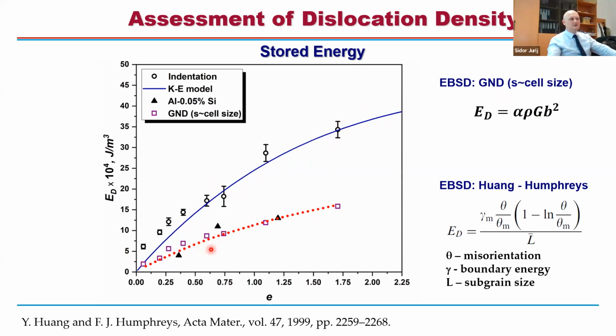And then I looked at the papers which were published almost 2 decades ago, the work of Huang and Humphreys, where they estimated the stored energy in aluminum alloys, also in almost pure aluminum alloys. And I was amazed that in fact those are our results, what we have seen. So based purely on GND, what we measure by EBSD, and those are the results of the work of Humphreys. By EBSD we nicely revealed the GND, and the amount of stored energy which they have estimated nicely correlates with the results which we also observed in our alloys. So it seems that those techniques are quite reliable.